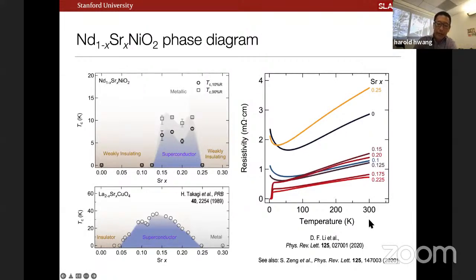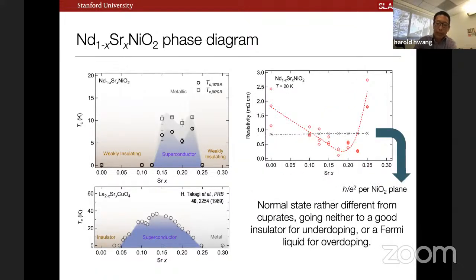The point we wanted to emphasize or think about was, at this point, a phenomenological observation that if we look at the low temperature normal state resistivity across this doping series, you would see that there is a relative minimum, and this dashed line across here is the scale of a quantum of resistance per nickel oxide plane. So qualitatively, what you can think of is that just when we dope or dip into a regime approaching coherent transport, this correlates with the superconducting dome. So I want to come back to this, revisit this problem later on. So let me not go into the details here.